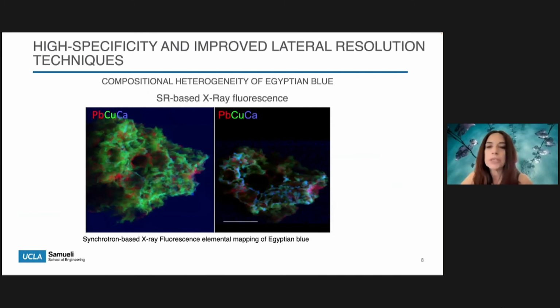So to improve detection and to address the issue of microheterogeneities in Egyptian blue, our samples were further analyzed using synchrotron-based X-ray spectroscopies. The elemental maps we see here of two Hellenistic Egyptian blue pigment samples from Delos in Greece show the abundance and spatial distribution of lead, corroborating previous data on the use of a lead compound as one of the raw materials used for the production of the pigment. While XRF alone was not able to provide additional information on the origin of the lead, the detection and identification of tin at a concentration of 0.8 weight% raised additional questions on the nature of the chosen raw materials.